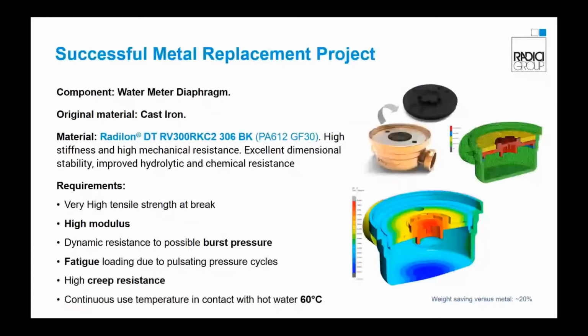For a customer operating in the water management sector, we were involved in a metal replacement project where a water meter diaphragm was redesigned and then validated through our CAE tools in order to substitute the original material, cast iron, with a polyamide 612 with 30% of glass fiber. This material is suitable for parts requiring high stiffness and high mechanical strength, and shows excellent dimensional stability and chemical resistance. Also in this case, the requirements for this application were quite severe. In particular, the fatigue and creep resistance, which were assessed through a structural simulation.